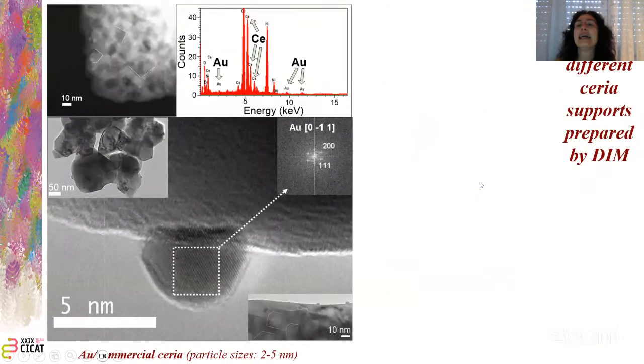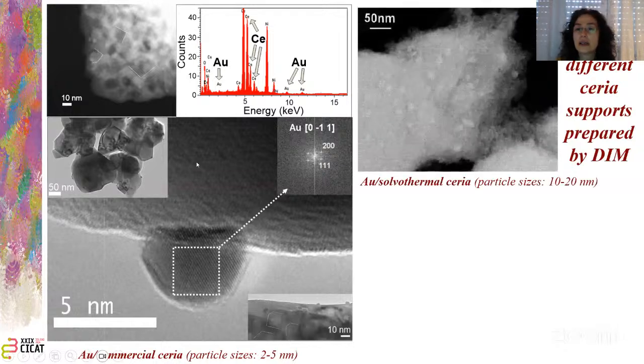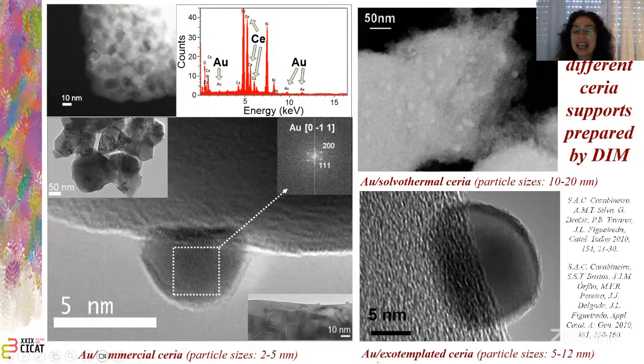That is the idea. Here we have some results of gold on commercial ceria, where we obtain very, very small nanoparticles, 2 to 5 nanometers, very good. The sizes were larger on gold on solvothermal ceria. If you remember, solvothermal ceria was the best support. And on exotemplated ceria, the particles were of intermediate size.